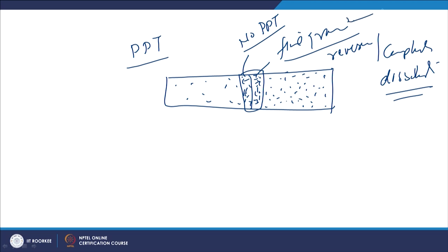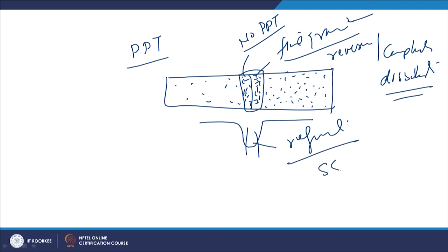In this situation, if we try to just see the properties of the weld nugget area, then we will notice that despite the refinement, there has been a sharp drop in the weld metal hardness and weld metal strength. So here there is a contradiction: despite the refinement we are getting a reduction in strength, because this metal was primarily designed to have the strength from the precipitates, and if these precipitates have dissolved, then refinement and solid solution strengthening will not be contributing that much as it was designed for the precipitation hardening.